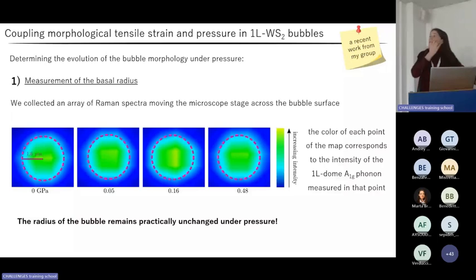In that way, we could build up a color map in which the color of each point of the map was assigned based on the integrated signal of the A1G peak of the monolayer dome. That procedure allowed us to get an imaging of the bubble at each pressure, even in the absence of a clear visual of this micrometric system inside the diamond anvil cell. And with these measurements, we could observe that, surprisingly, the bubble diameter remains practically unchanged under the application of pressure in the 0.5 gigapascal range.